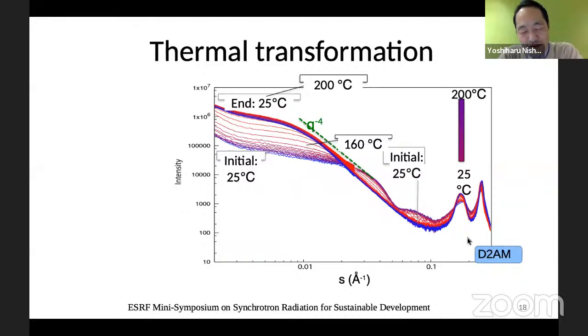So again, related to this first example of pulp recycling, where the pulp is going through cycles of wetting and drying and heat. Here, we wanted to see what's happening when the wood is subjected to high temperature and wet condition. So here we just started from a wet wood chip, and we heated up to 200 degrees. And this color code represents the evolution of the scattering profile of the anisotropic component.